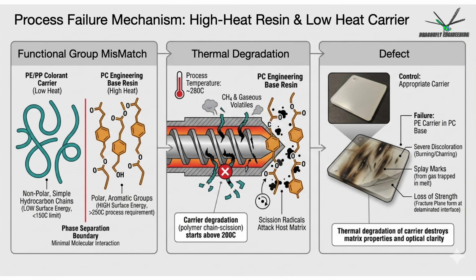So if you pick a base resin and a colorant resin that are the same, everything should go well. But let's talk about what happens whenever you pick a high heat base resin and a low heat carrier resin. For this example, we'll consider a polyethylene or polypropylene colorant carrier and a polycarbonate base resin. The low surface energy, nonpolar polyethylene or polypropylene hydrocarbon bonds do not bond with the high surface energy, polar aromatic polycarbonate groups. This will result in a phase separation because of the lack of interaction between these two types of materials. We also have a thermal problem here because the polyethylene or polypropylene will break down at temperatures well below the 280 C needed to process the polycarbonate.